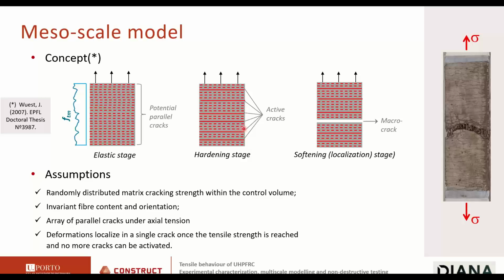As we will see, a crack very close to one that has been activated cannot be activated. We will provide some criteria for this. So some of the cracks will be activated during the hardening stage, until you reach the peak stress and one macro crack will form, the material will enter the softening stage, and the remaining cracks will unload. Okay, so we consider that in our specimen, the fiber content and orientation are all the same.